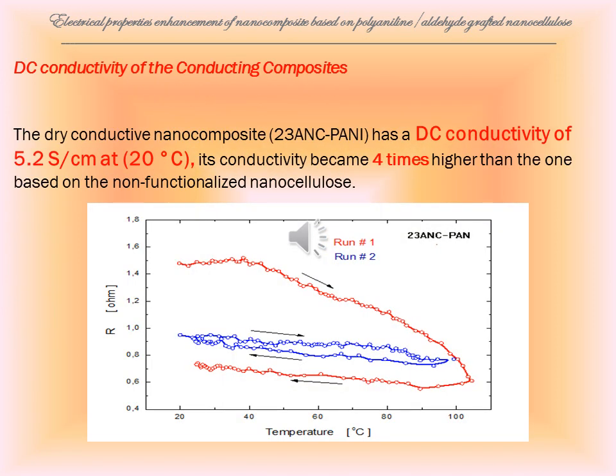In this work, we have studied the DC conductivity of the prepared composites as a function of temperature. As shown in the graph, the dry conductive nanocomposite 23 ANC PANI has a DC conductivity of 5.2 siemens per centimeter at 20 degrees Celsius. Its conductivity became 4 times higher than the one based on the non-functionalized nanocellulose.